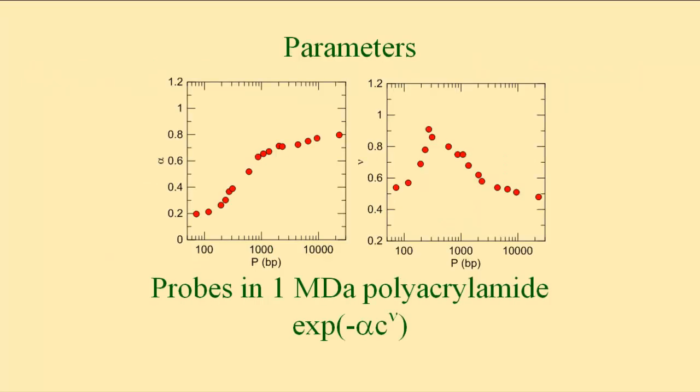That explains immediately why linear chains and star chains of the same size have very nearly the same electrophoretic mobility, namely they're using the same mechanisms, and fine differences in topology aren't doing anything. That's exactly the opposite of reptation pictures, in which linear chains can reptate, slither like a snake through a matrix, but star chains must use a totally different mechanism for advancing. Well, electrophoresis appears to refute that interpretation.